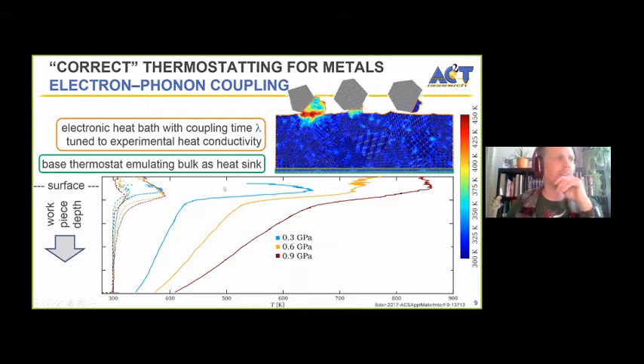And you can get a good, let's say, first guess from the Sommerfeld theory for metals for this lambda. But all of the papers that I read say, yeah, it's a guess, but you're going to be off by at least a factor of 2 or 3. So you have to do your own simulations. You do some preemptive simulations. You try out a couple of lambdas, and you measure these gradients.